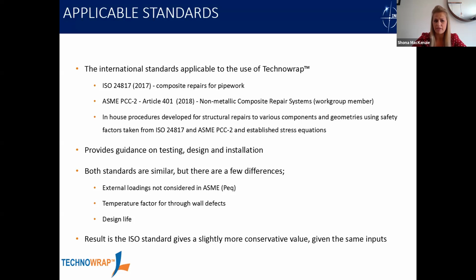The main difference being the design life. So ASME classifies defects as short and long term, I believe. Gareth, you might want to correct me on that. And ISO is anything up to 20 years, depending on the design conditions. Also, external loadings and temperatures are not considered within the ASME document. Sorry, temperature factors for through-wall defects only is not considered. So basically, as a result of that, the ISO standard gives you a slightly more conservative value when given the same inputs to both. So also off the back of that, we have, sorry, Don, if you could just move on to the next one.